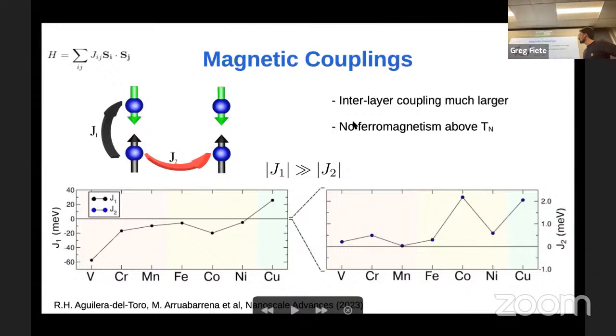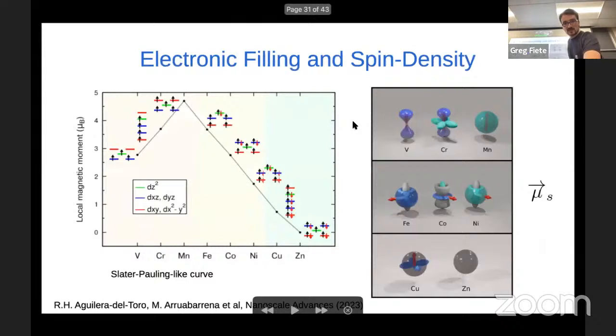Okay. Yeah, let's move on. Well, all of this magnetism is also very related to electronic structure. Here we plot the local magnetic moment of each element regarding a filling model we did, where we divide the electronic d orbitals into 3 groups, let's say. In red we have the orbitals that are just in plane, in green is the dz squared out-of-plane orbital, and blue is the orbitals with both in-plane and out-of-plane components. After exhaustive calculations and band structures and trying to fit everything, we derived this band filling model, which also yields the local magnetic moment.